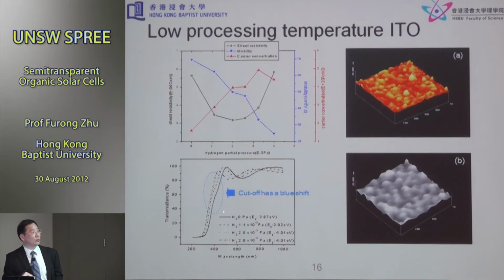This is very useful, because this is typically good for display applications. For organic solar cells using conventional ITO, the black solid line curve here, the transparency in the short wavelength range is typically around 50%. With this technique, you'll see there's a clear blue shift. The dotted line, at the same wavelengths, the transparency is much higher. It can be increased from 50% to 80%. Now this is probably not a big deal for organic solar cells, because you don't have many photons in this range. But for display, it is very important.